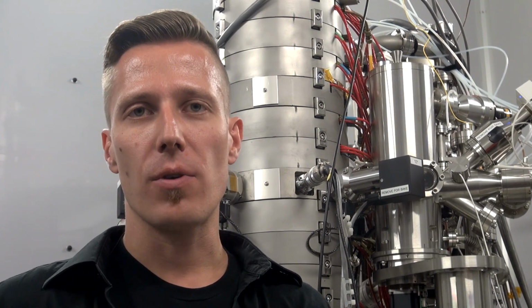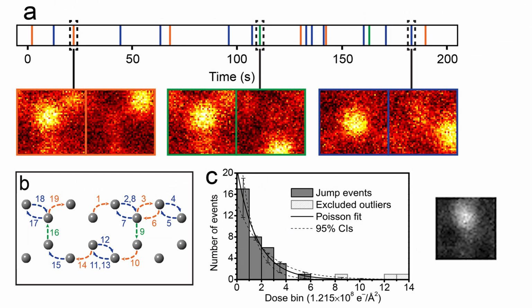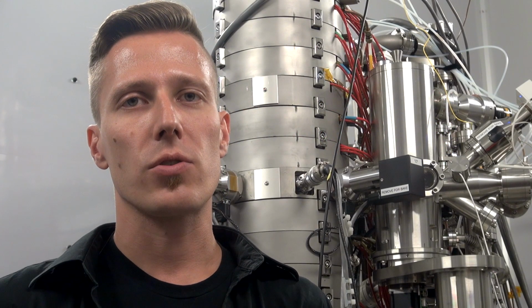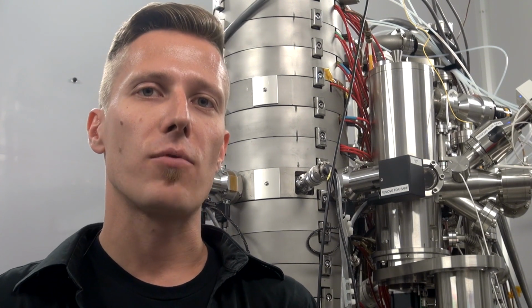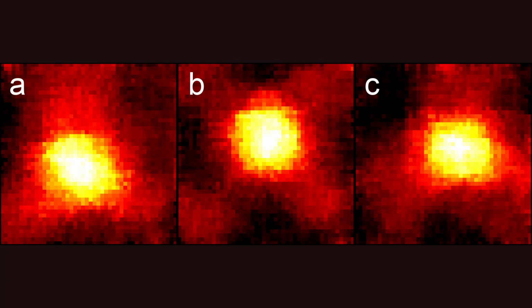We were further able to analyze the experimental data, consisting of 38 such jumps, 19 of them in an unbroken continuous time series, as a stochastic random process. Knowing the electron dose on the sample, we were able to calculate the probability of this process happening and compare it directly to simulations, and obtain really good agreement between theory and experiment. We further looked at some other processes that are less likely, experimentally speaking, and we were able to explain why this is so from first principles.